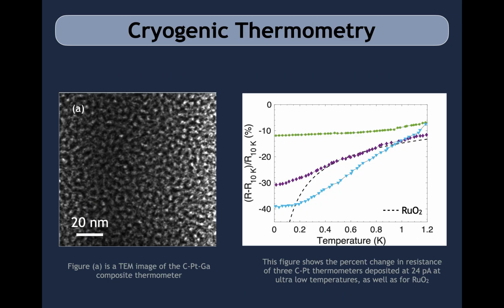At low temperatures, it is critical that we are able to measure the local on-chip temperature. To do that, we developed highly sensitive, focused ion beam deposited carbon-platinum resistive thermometers. In the left image, we can see the small white platinum nanoparticles suspended in a black carbon matrix. Both platinum and carbon are good resistive thermometers on their own, but platinum loses sensitivity at around 10 Kelvin, and carbon thermometers are difficult to use for local microscale measurements like we need here.